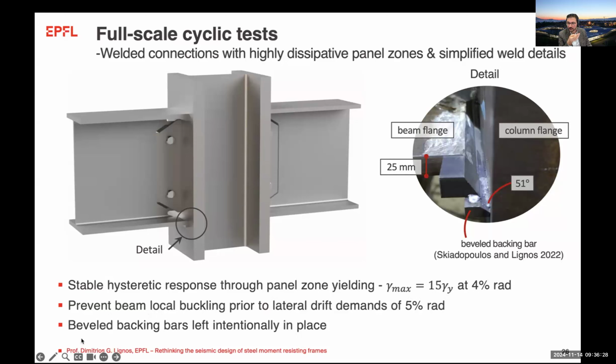And the third one relates to weld technology, and in particular beveled backing bars that are left intentionally in place, so that we can examine if this really does work, because that would be a very interesting thing from a fabrication standpoint. So here you see the panel zone geometry, as well as the beveled backing bar that was left in place prior to welding, including the bevel I showed before that we used in the simulations that I showed in the previous slide.